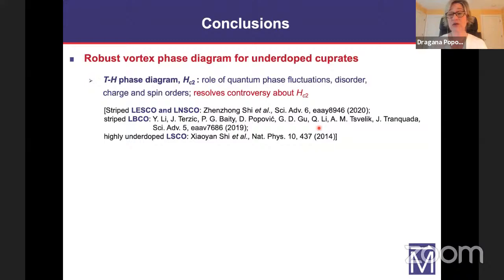Also, recently, we worked with the group of John Tranquada on LBCO, and also found evidence that superconducting correlations persist even beyond the melting field of the vortex solid. So based on all this and general arguments, again, we expect the same thing to be seen in other cuprates. In YBCO, for example, as I showed at the beginning, there have been reports or claims that the vortex liquid does persist at very low temperatures.